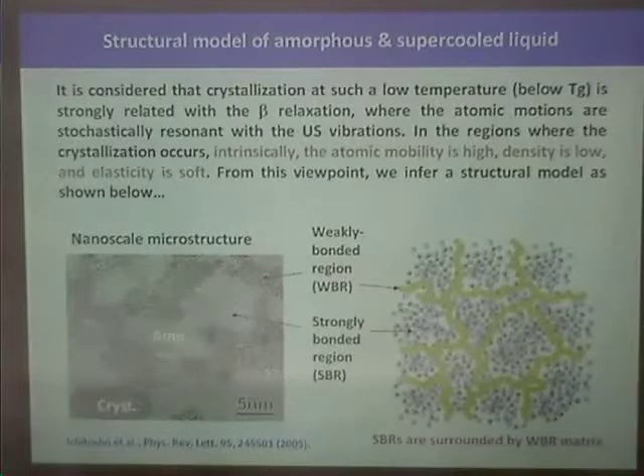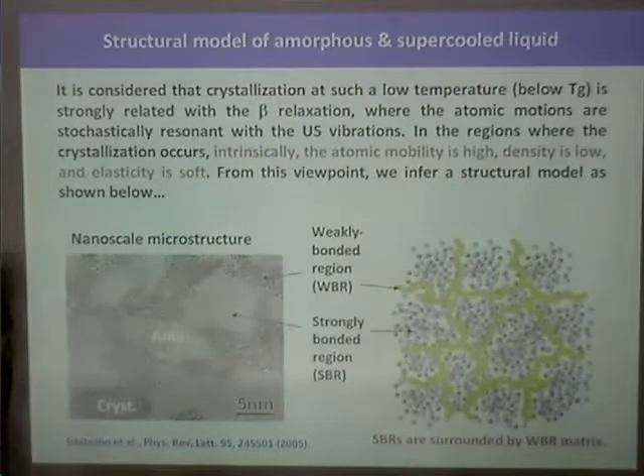Usually, at this temperature, crystallization does not occur without ultrasonic vibration. Under the ultrasonic vibration, there is stochastically resonant atomic motion, and that leads to the crystallization. So in that case, this is intrinsically... The ultrasound can nucleate crystals.